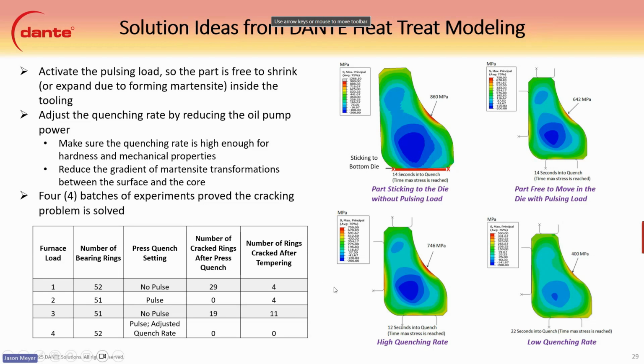So the 4 batches that they ran some experiments on. The first one was the baseline that they had before, and they ran it with no pulse, and you can see a lot of them were cracking, about 60% or so. They ended up running a batch with pulse, and only 4 of them cracked during tempering, and none of them after quenching. They redid the first test here, and it had similar results to test number 1. And then the pulse load with the reduced quench rate resulted in no cracks whatsoever through the entire batch. So I'd say that's a huge success.